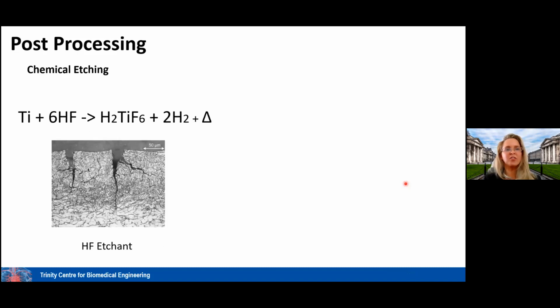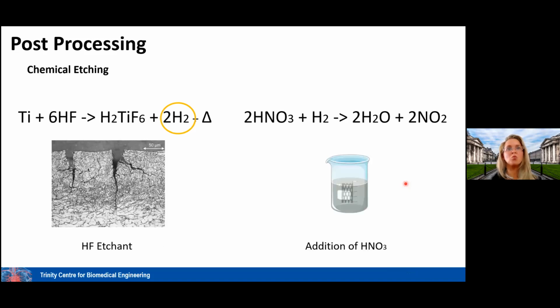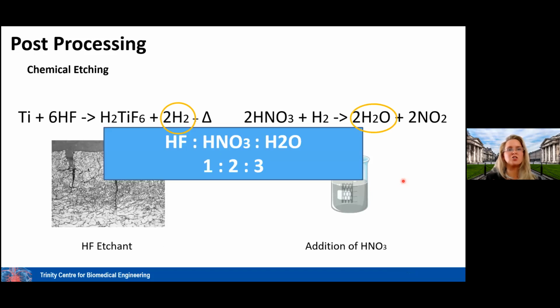The type of chemical etching you'd have to use for the stents that we're printing here, which are titanium stents, requires you to remove titanium, which would require hydrofluoric acid. And hydrofluoric acid, when you etch away, will produce a lot of hydrogen. That can result in cracking of the structure, having that hydrogen embedded in it. So we have to add nitric acid as well to remove that hydrogen, as you can see here, and turn it into water and nitric oxide. So that's what we use: a chemical etchant solution that has hydrofluoric acid, nitric acid, and water, to ensure that we can remove material and also potentially give us flexibility in design.